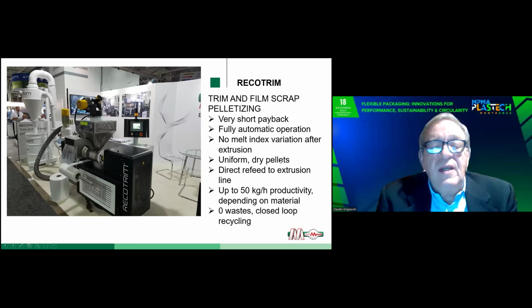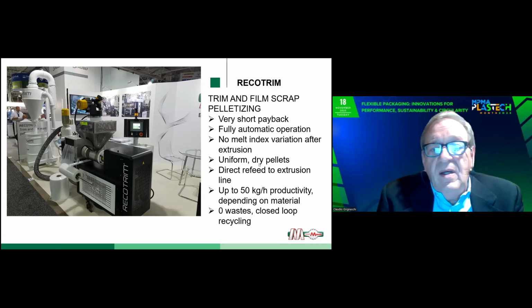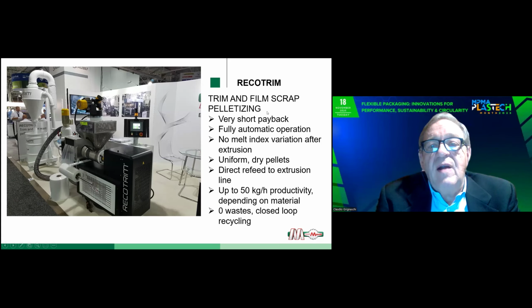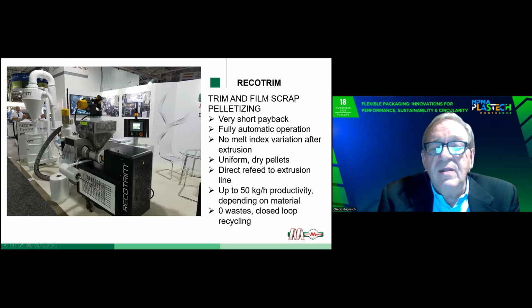And then, as a last point, this is a very, very strong point of the Macchi production, our RecoTrim. The RecoTrim is a trim and film scrap pelletizing machine. Fully automatic, no melt, this guarantees no melt index variation after extrusion. Fully only air cooled, no water involved in the cooling of the pellets, because it runs only with the polyethylene scraps and trims.